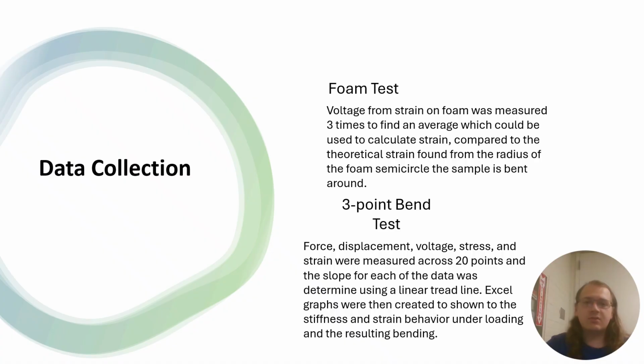In the foam test, voltage from the strain was measured 3 times as it was bent around a foam semicircle, and was used to calculate the strain again, which was compared to the theoretical strain found from the radius of the foam circle itself. In the 3-point test, force, displacement, voltage, stress, and strain were measured across 20 points in time, and the slope was found using a linear trend line. Excel graphs were created to show the stiffness and strain of the sample under loading and the resulting bending.